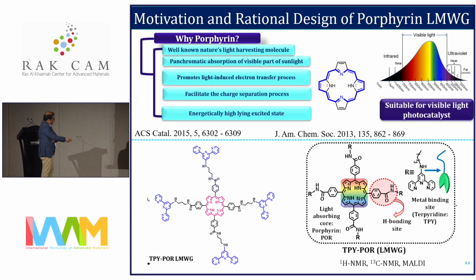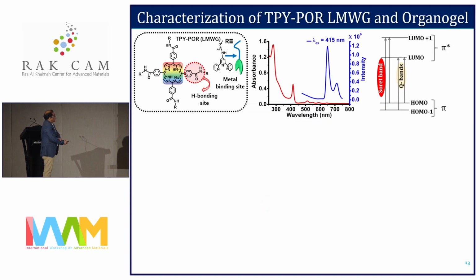In our design, we have the porphyrin core, framed with tetracarboxylate molecules, and through an alkyl amide chain, we connected a 4-terpyridine module which can bind a metal site. This metal site can be covalently attached, forming 3-dimensional higher order architectures, where electron transfer can happen from the porphyrin core to the metal sites.